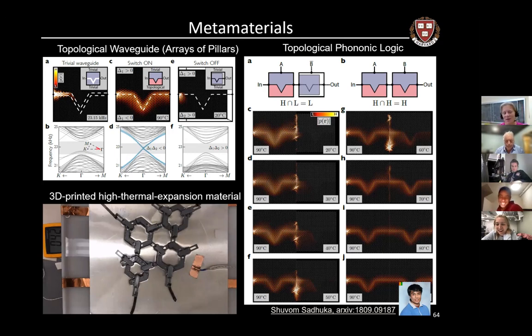Why? I mean, we started it because it was cool, because how do you understand quantum mechanics? Nobody can understand it, right? So our attempt was to try to understand it by building something that was macroscopic and tangible. And I think at this point, our argument is that a metamaterial has continuous tunability. So if we build our metamaterial as air cavities in a plastic matrix, then each air cavity acts like an individual atom, and we can continuously tune the size of that air cavity because it's a macroscopic thing. You can make it 3.1 millimeters, 3.2 millimeters, et cetera. So in the periodic table, you have 100 discrete elements, and that's what you're stuck with.